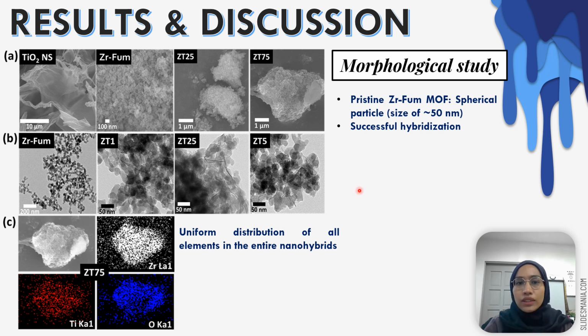Okay, for the morphological study, we can see that here the TiO2 nanosheet is successfully prepared and it shows a very thin two-dimensional sheet-like structure. Meanwhile, the pristine zirconium fumarate MOF shows spherical particles with a size of 50 nanometers. And the successful hybridization between the TiO2 nanosheets and the MOF can be shown in this TEM image, in which we can see that the nanoparticles of MOF are uniformly distributed on the surface of the TiO2 nanosheets. And from the EDS study, we can also confirm the existence of uniform distributions of all elements in the entire nanohybrids.